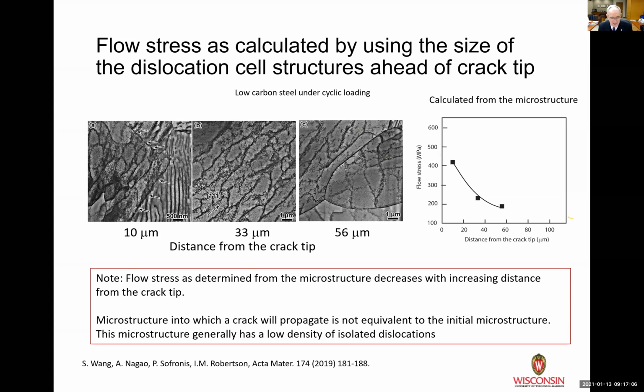Now, one of the things that you can do, and this is all the work of Shui Wang, so Shui should certainly get the credit for doing this very, very elegant work. Because what he then did is he said, okay, if I measure the cell size, I can actually relate that microstructure I see to a local flow stress. Right? So you could calculate the flow stress related to the microstructure from knowledge of the dislocation cell size. And that's what you see over on the right-hand side. You'll see that as you move with increasing distance from the crack tip, you'll see that the flow stress decreases.